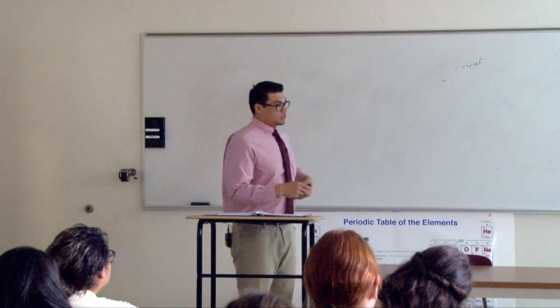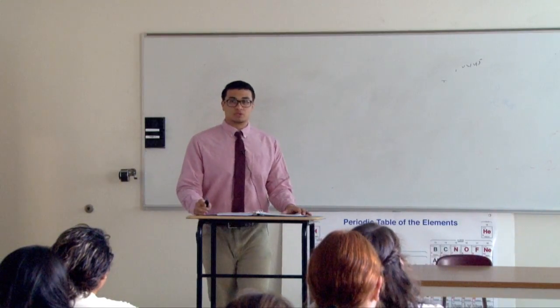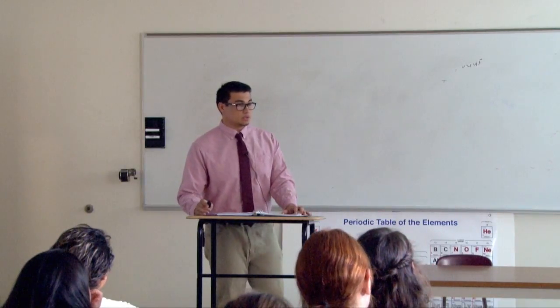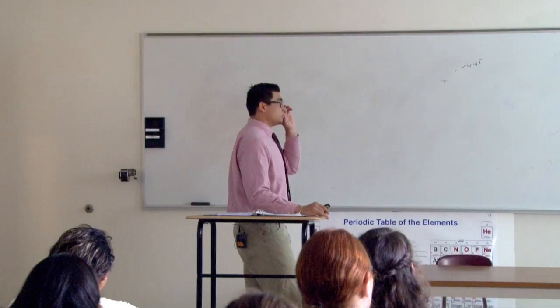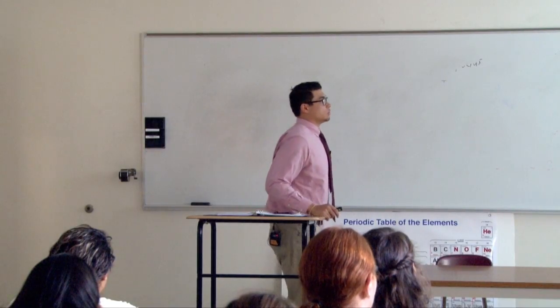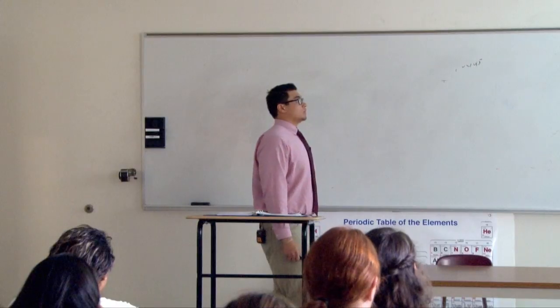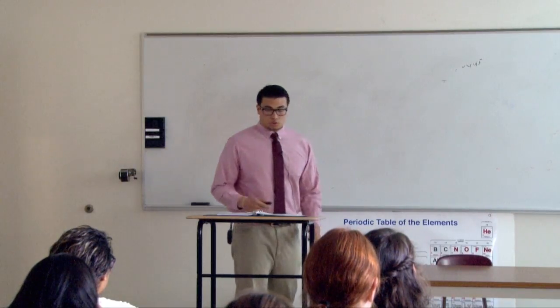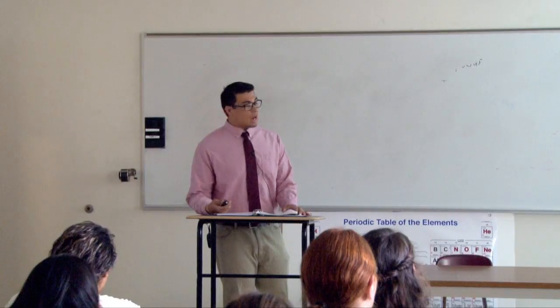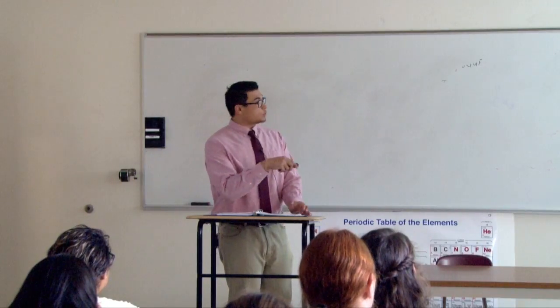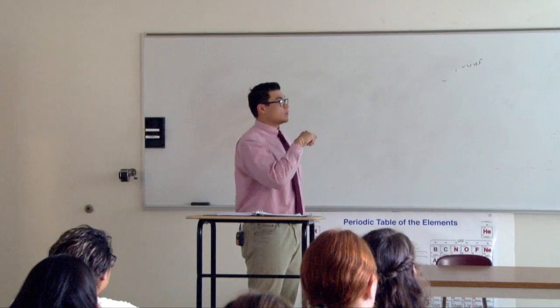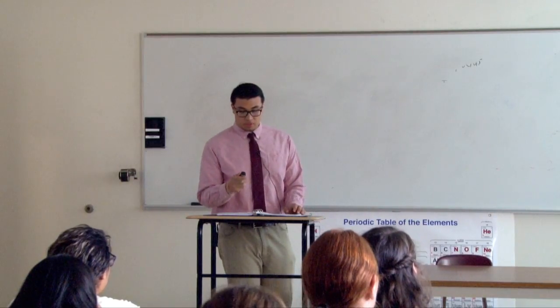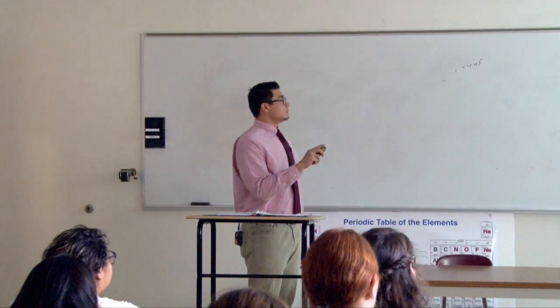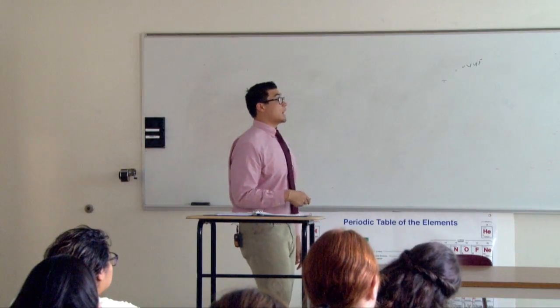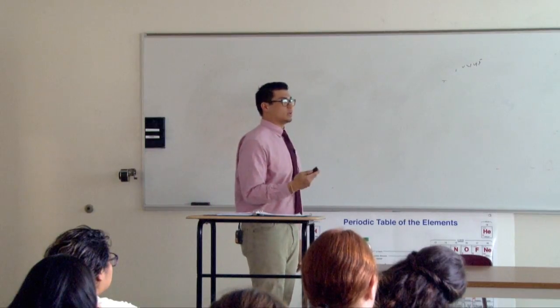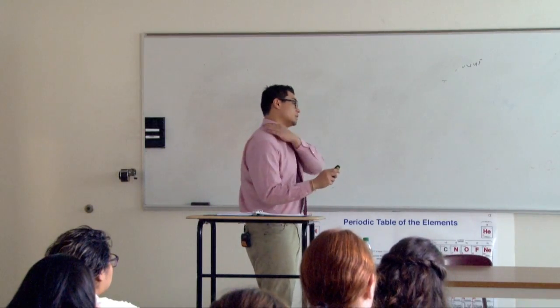Moving on to present day, just like with the thermal batteries, the idea of having mixtures of ionic liquids poses to be more of a support system than doing it by itself. So they came up with weight percentages of 14.5 of 1-allyl-3-methylimidazolium chloride, and a 16 weight percentage of the 1-ethyl-3-methyl imidazolium acetate. It increases the solvent power using these two together, which can also be improved with dimethyl sulfoxide, DMSO, and it also reduces the reaction time, which is something that we look forward to when running experiments. So here's just a quick picture of applications, used a lot for fuel. I know in clothing, maybe even shelters and stuff like that. So cellulose is widely used.